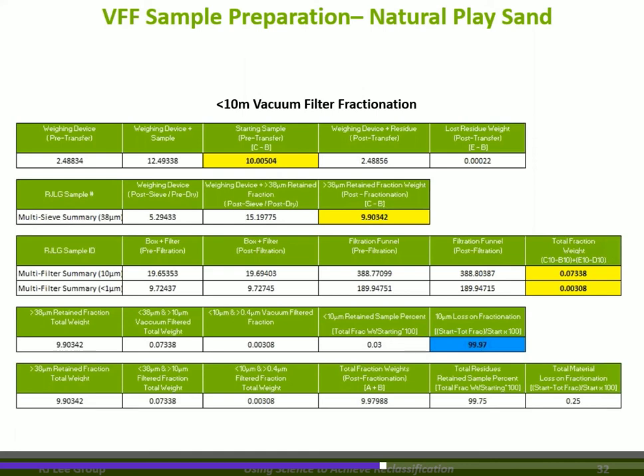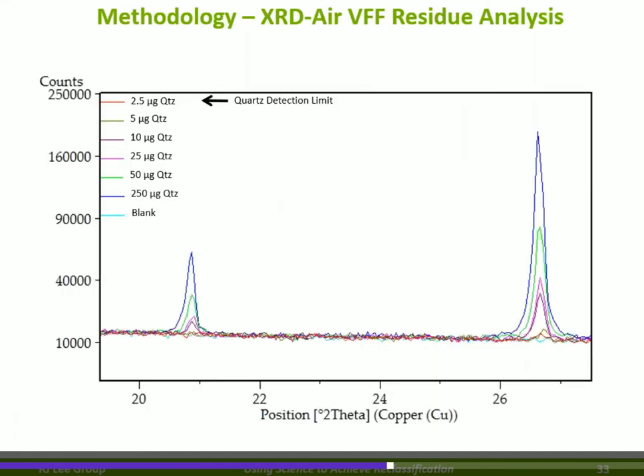How good are we at what we do? At the very bottom right, you'll see that our total loss on fractionation, from that 10 grams all the way through, we have accounted for 99.75% of the material. In the process, we've only lost 0.25%, which can occur on surfaces, into the air, or wherever; we don't know. But we like fractionations that end up with less than 1% loss, because that means we did a nice, clean, very meticulous process. All right, so now we've got our residue.